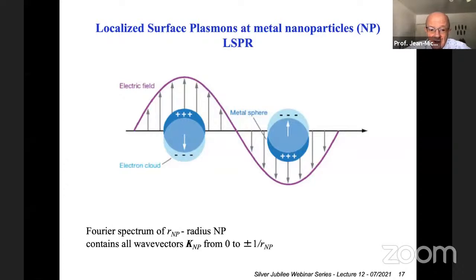The absorption of the light by a metallic nanoparticle will be proportional to its volume, because the dielectric constant of a metal is complex. So there is a part which is just a reaction to the light, which is in phase with the light, but there is a part which is in phase quadrature, which corresponds to an absorption. When we cancel the real part of the dielectric constant of the metallic nanoparticle in the denominator, it makes an enhancement of the absorption, and we are left with absorption. So that absorption varies like the volume of the nanoparticle.